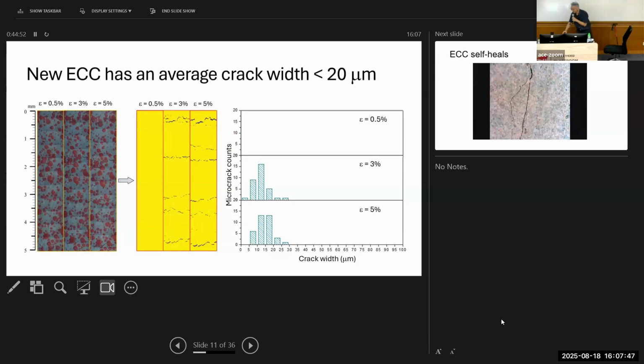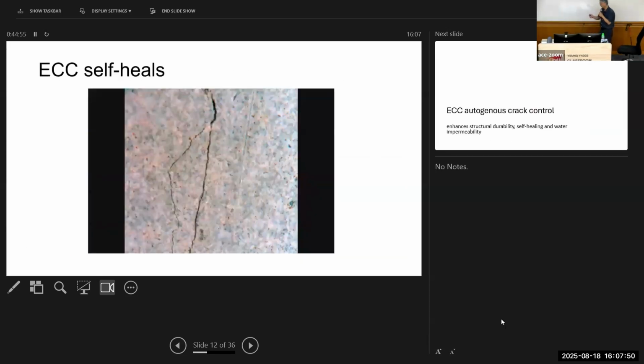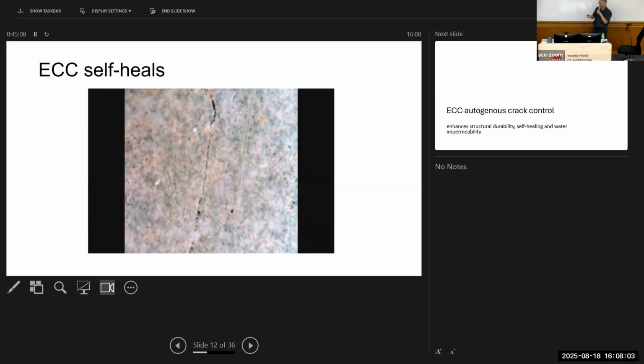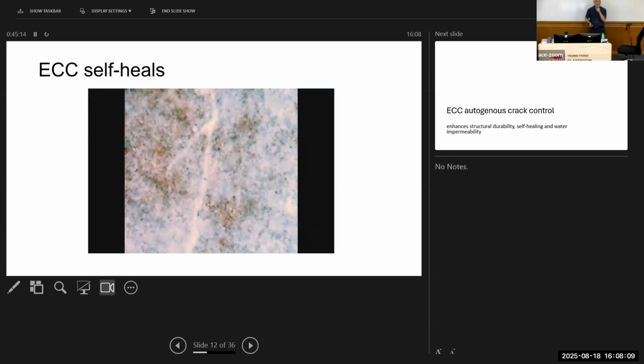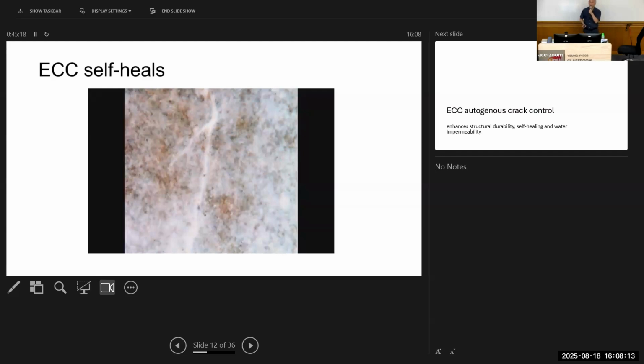Now, what is even more remarkable is when you make the crack so tight, look here, if only I can activate it. This is a specimen that I have deliberately damaged and then exposed it to air and humidity. So these cracks repair themselves. Okay, there is a chemical process going on. It's very, very simple. It's not any secret here. It's just continued hydration of the unhydrated cement grains. And there are some carbonation effects because the air has carbon dioxide. So there are calcium carbonate crystals inside there when you look into the material.